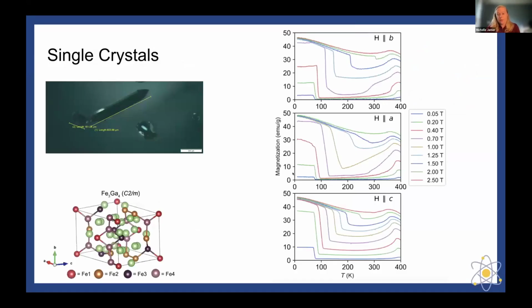So in the single crystal work that was published in 2022, we were able to find the magnetic behavior along each individual crystallographic axis. So in the graphs, what we have is when the field is parallel to the B axis, the A axis, and the C axis. As you can see, the magnetic properties change a little bit in terms of their inflection points along each crystallographic axis. And while there are different inflection points, maybe slightly different features, essentially it has the same magnetic behavior.